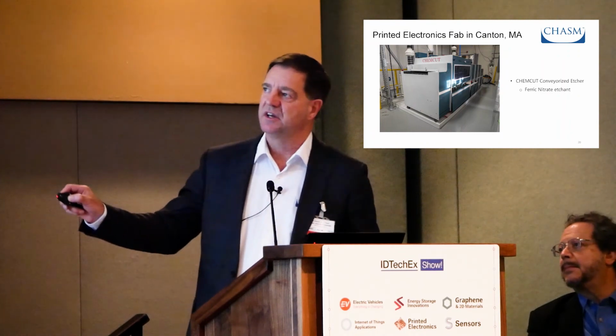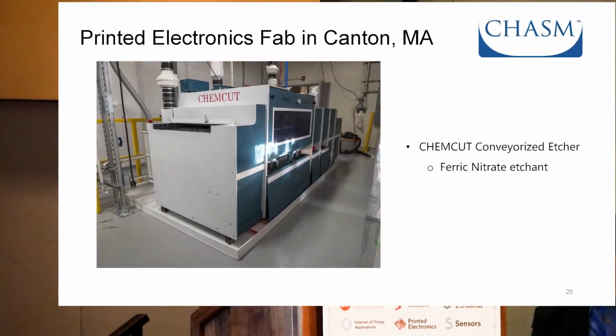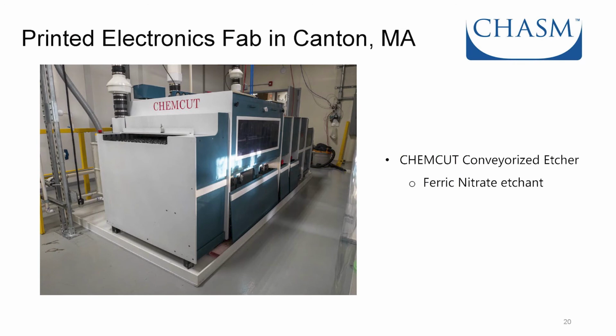We also have an etcher. This is an industry standard Chem-Cut etcher. It's a conveyorized etcher. We use ferric nitrate etchant. Most common etchant for copper is cupric chloride or ferric chloride, but ferric nitrate is a very good etchant for silver, and it also is a decent etchant for copper. And so we use ferric nitrate etchant because it can etch both the silver nanowires and also the copper metal meshes.